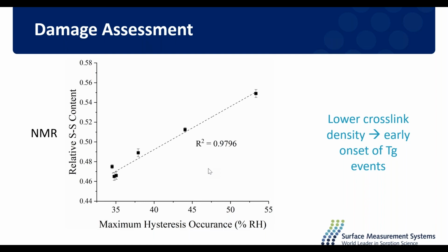Someone asks here, if the methyl group reduction had such a significant effect on the hydrophobicity of the hair, wouldn't you have expected the methyl signal from the NMR analysis to increase significantly? Well, this is again down to the natural abundance of carbon-13. It is pretty low, even with using as much sample as possible and cross-polarization methods. If you think about how many carbons are in hair in total, and how many disulfide bonds we're reducing, the actual amount of methyl groups we're adding is not very much. Considering their natural abundance is so low, it becomes more understandable why we wouldn't be able to see it with NMR, but perhaps with a different analytical tool.